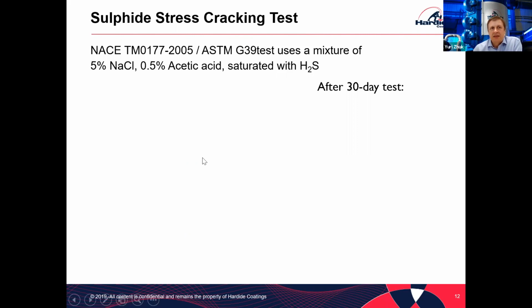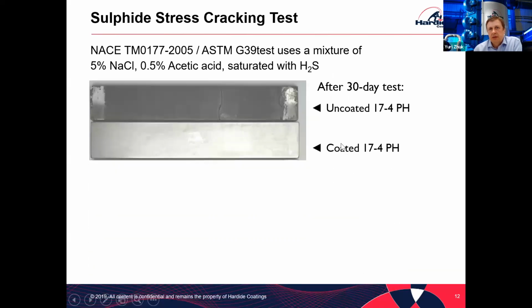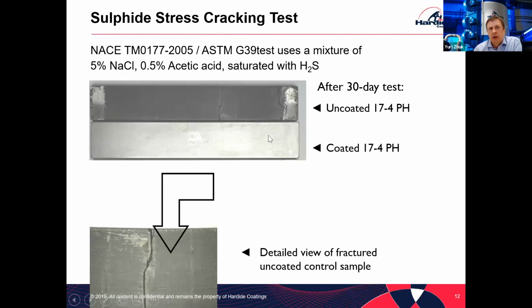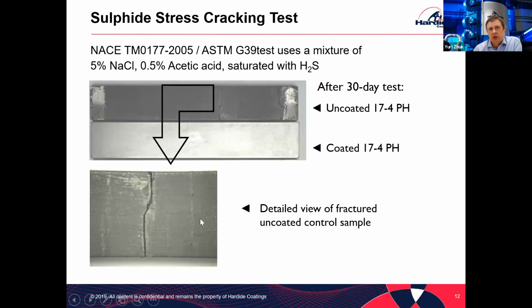So in this NACE test, it was tested in a mixture of salt, acetic acid, and H2S. So 2 samples shown here. The top one is an uncoated control, and the bottom one is the same substrate with Hardide coating, both after a 30-day test. You can see the difference. The uncoated control was actually broken into 2 pieces. That's a magnified view.